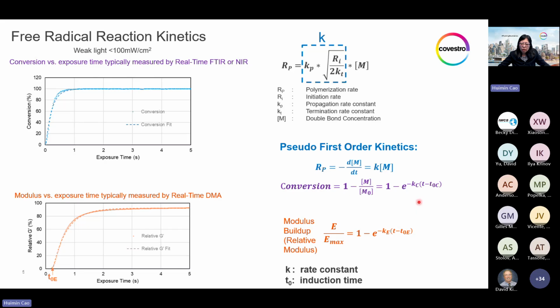And for modulus buildup, it also follows the first order kinetic curve, which you can see here is the real-time DMA. The experimental and the fitted curve fit perfectly well, and the Ke is the reaction rate constant. And it should be noted that the Ke and the Kc are typically not equal to each other. T0 is the induction time where this curve started to rise. And T0E is always longer than T0C because it takes time for the reaction to pass the gel time, turning from liquid to solid when elastic modulus starts to be measurable.